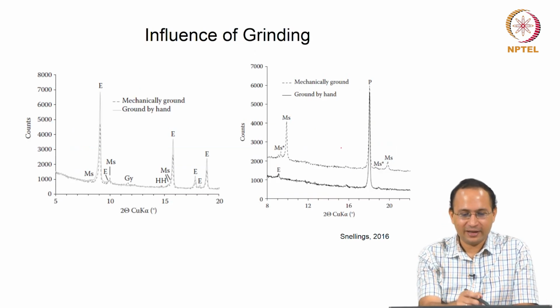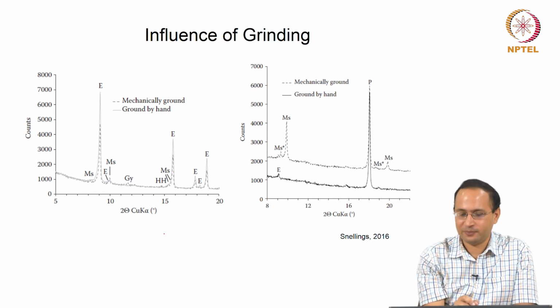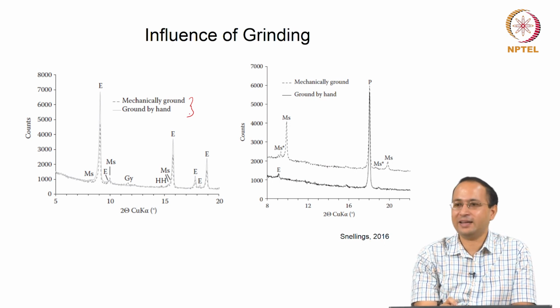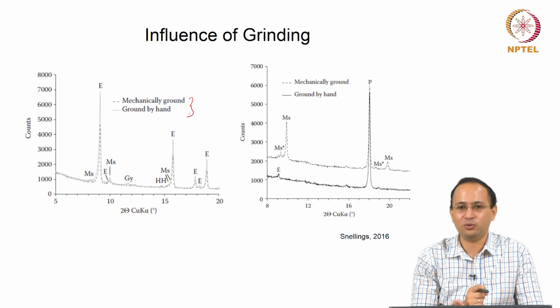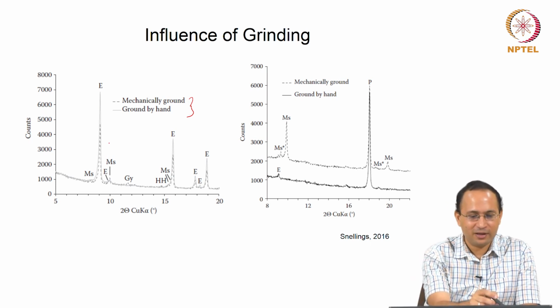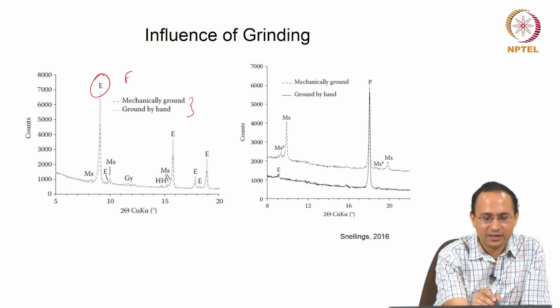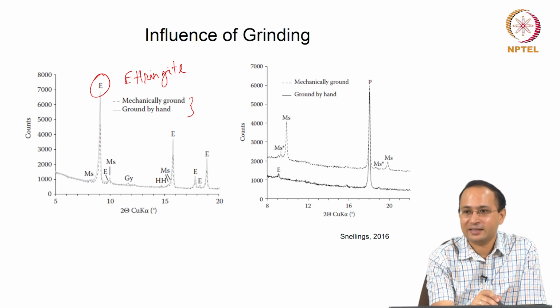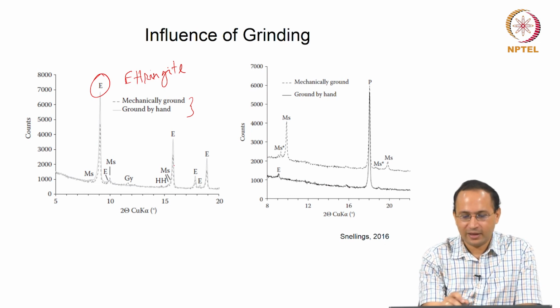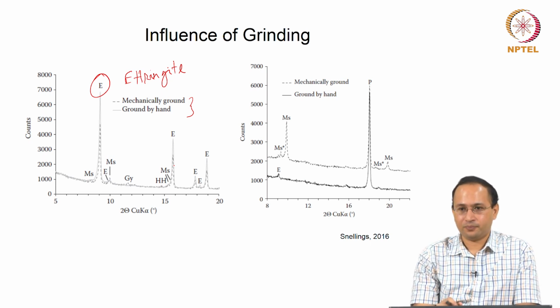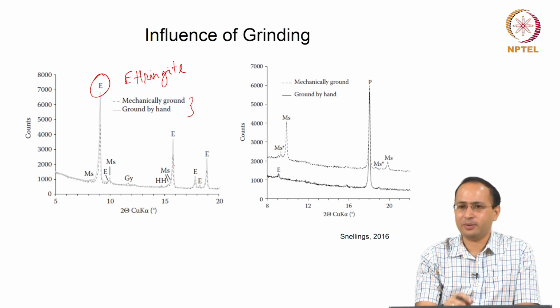So in this case you see this is a cement paste sample, X-ray diffraction, basically you see intensity versus 2 theta, right. So here is the comparison between mechanical grinding and grinding by hand. Imagine you have two different processes. In one you are mechanically grinding your sample, in one you are hand grinding. So see the effect, especially if you pay attention to the peak E. E is basically Ettringite. It is one of the phases you have in your cement paste. Okay. So the intensity gets affected, right. In the mechanically ground sample, the intensity is lower. You see it clearly, right. It has to do with the temperature rise. In the mechanically ground sample, maybe the temperature was higher, and it led to decomposition; part of the Ettringite got decomposed, right.